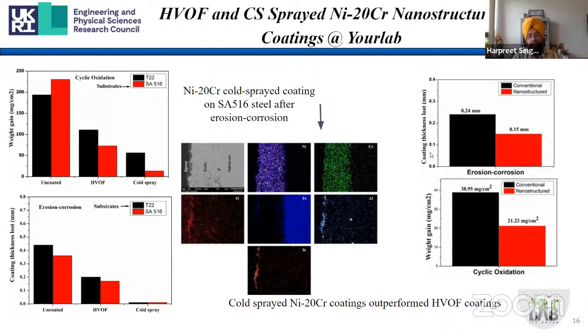But the challenge which we faced was that our powder feeder did not support us during cold spray or even HVOF spray. So flowability was a big problem at that point. This was around 2014. So what we did was use those nanoparticles with our micron size particles and make some mixtures out of them, and we tested them. Because these powders are milled, we could have some kind of nanostructures in our coatings. We benchmarked them against our normal micron size nickel chromium coatings, and then these blended ones, and we could see that we could enhance the properties of these cold spray coatings through the addition of these nanoparticles in certain fractions in the micron size.